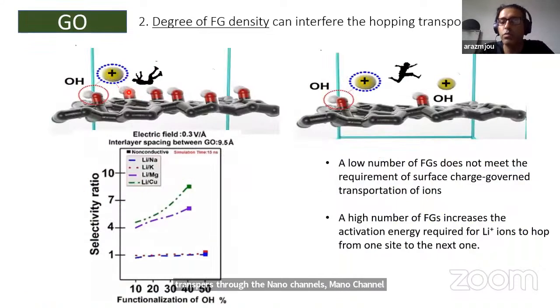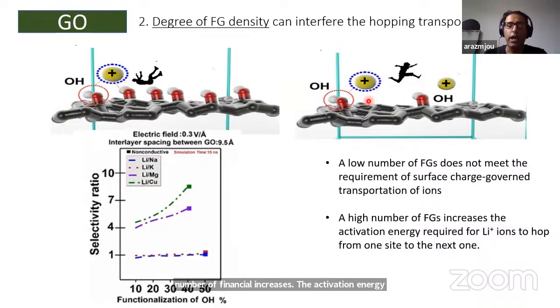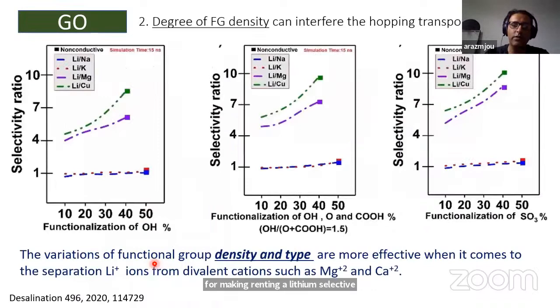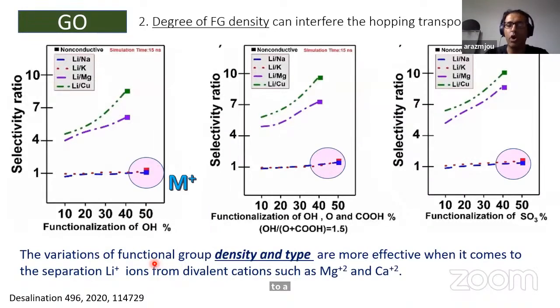In terms of functional group, it's also important. A low number of functional groups does not meet requirements of surface charge governed transportation of ions. A high number of functional groups increases the activation energy required for lithium ions to move from one side to the next one. And what we found is that functional group density between 10% to 50% is ideal for rendering a lithium selective membrane. We also found that variation of functional group density and type are more effective when it comes to the separation of lithium ions from divalent cations such as magnesium or calcium cations.